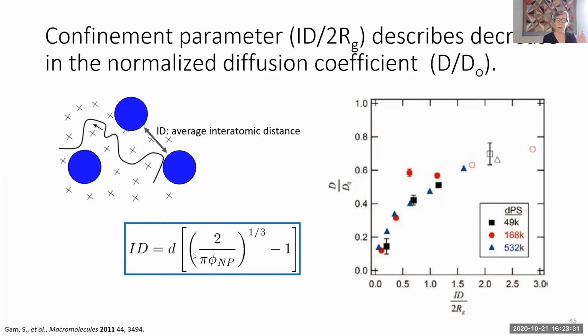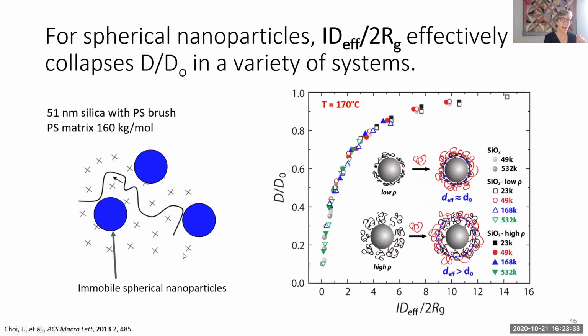And then there were many more papers, and I'm just going to skip to the end, where this is a compilation of years of work, where this is the bare particle, the gray data points. You can just see how lovely this collapses for polystyrene on silica, phenylcap silica. So again, a very athermal surface. If you have bare particles, if you have particles with a low grafting density or a high grafting density.